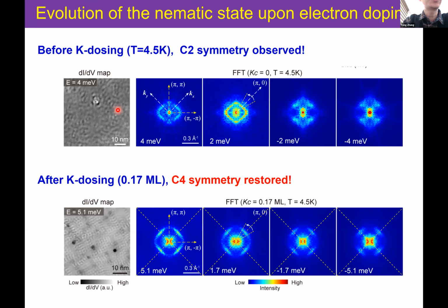So we checked the QPI before and after potassium doping. Before the doping, we still see this C2 symmetry breaking, which is also along the pi direction. So we can repeat our results on different samples and a different STM system. But after the potassium doping, you see the C4 symmetry is restored. I show the perfect C4 symmetric QPI patterns. We think it's because the electron doping drives the system out of the hole doped region, so the nematicity disappeared.